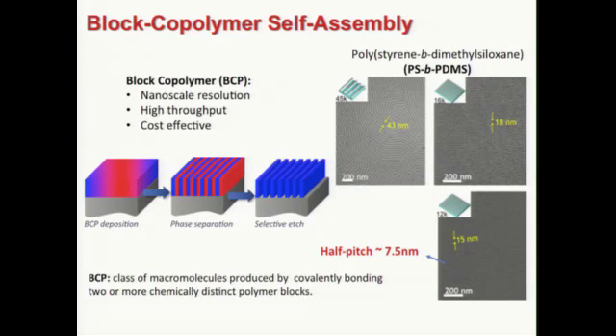So here in this work, we use the Block-Copolymer technique, which is a bottom-up approach. Instead of exposing a resist, here we have two distinct polymers. We mix them, and then I spin it on the surface, and then you have the phase separation, either by a solvent treatment or a thermal treatment. These two phases separate, and they form a kind of periodic nanostructures. And then eventually we selectively etch one of these blocks.